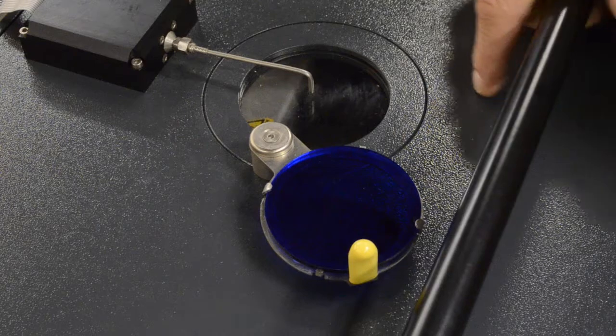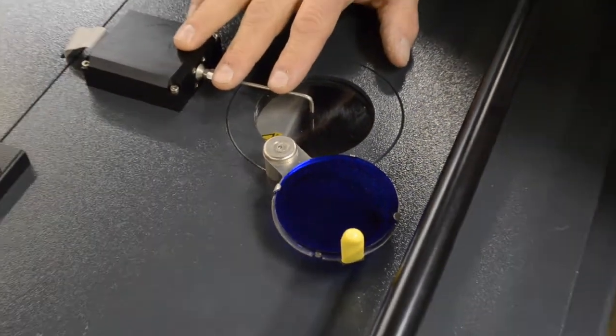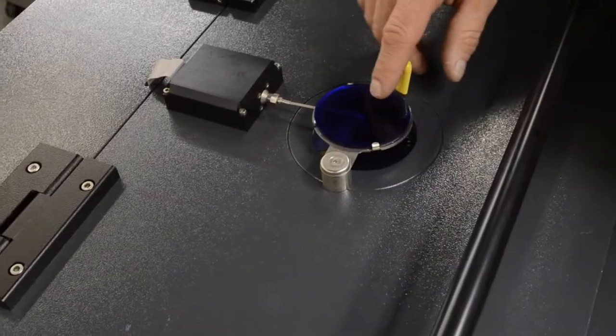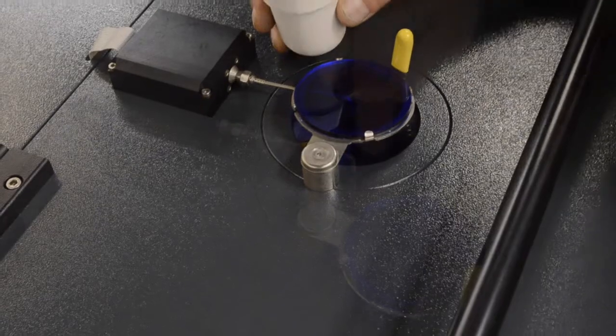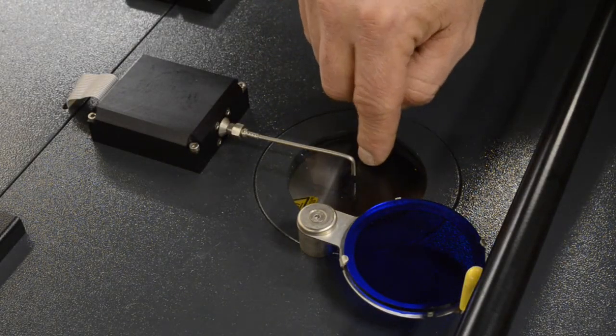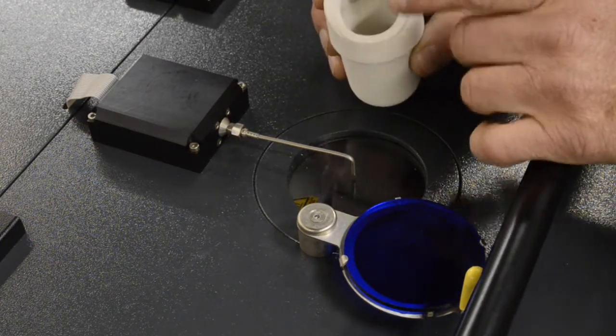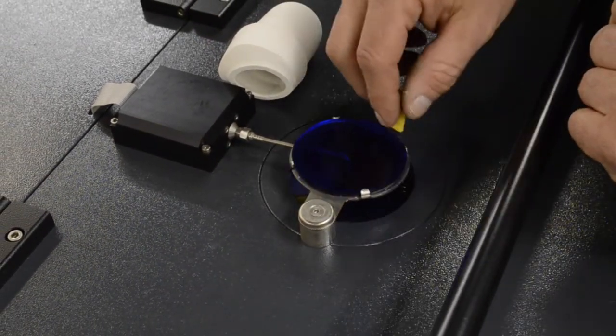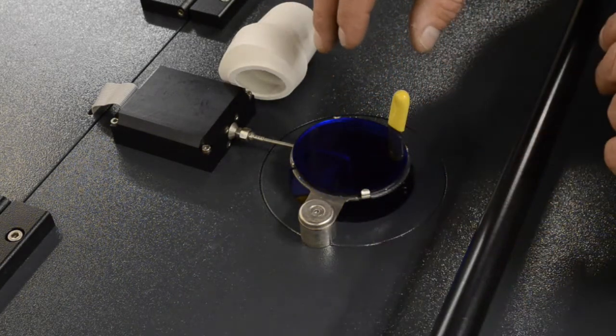What's actually reading the metal temperature is the optical pyrometer right here. When you're doing platinum or other high temperature metals, you want to use your protector, the lens right here, which allows the operator to look at the crucible, at the platinum crucible, when it's reaching full temperature. It reads through the protective lens, and it will tell us what's the temperature of the gold crucible or the platinum crucible of the metal inside. When you're using platinum, which gives out a lot of brightness, it's very bright, you want to close the protective lens, and that allows the operator to see without or minimizing the chances of hurting his eyes.